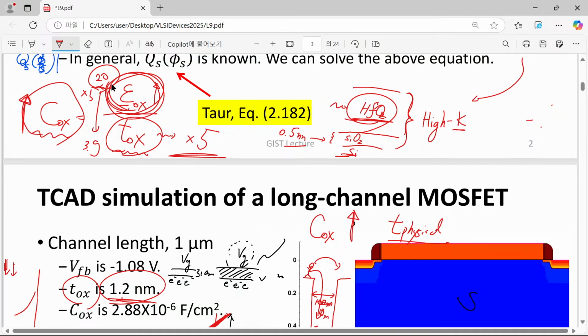So although we can introduce high K material, what happens? Let's assume the extreme case. If we reduce the thickness of high K material to zero, an infinitely thin high K layer, we will still have a certain number corresponding to 0.5. Of course, if we make just 0.5 nanometer thick pure oxide, then our transistor will stop working, because there will be tons of gate current, and gate leakage current will grow exponentially, so it's not possible. So after using this high K material quite happily for 20 years, we are once again at the end of this technological limitation.